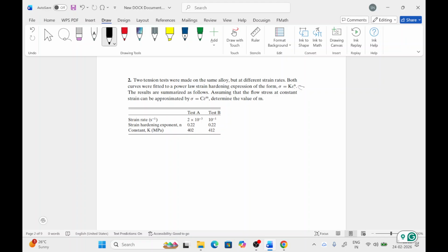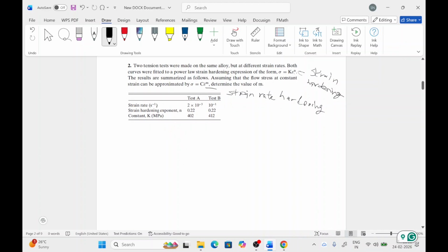One more thing I have to say. This is the strain hardening behavior, and this is the strain rate hardening. So to a power law, the results are summarized in this table. Assuming that the flow stress at a constant strain can be approximated by this equation, determine the value of m. We are given strain rates and the constants, so we have to find the sigma value for both test A and B, and by putting in the second equation, we can find the m value.